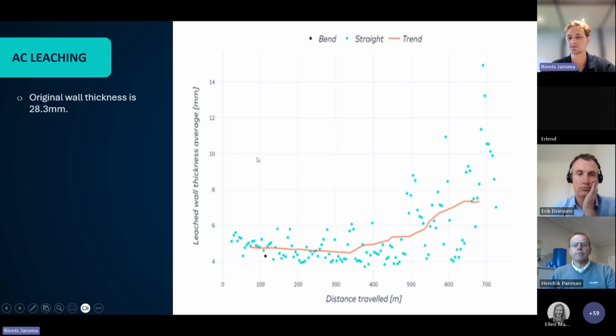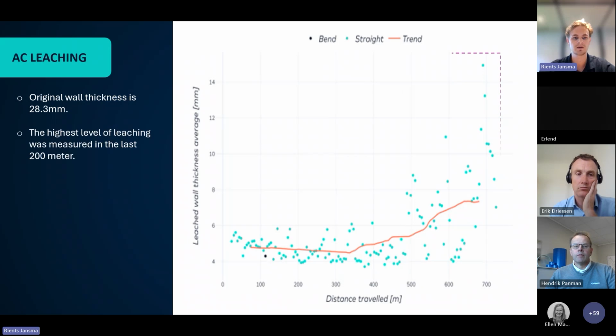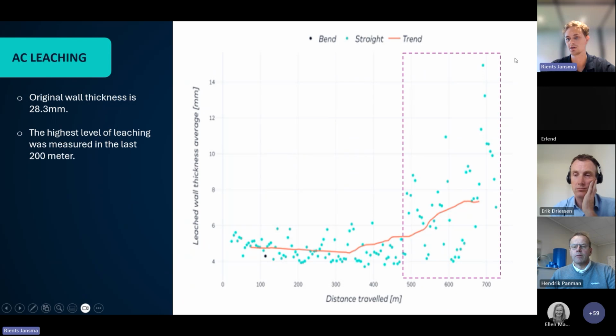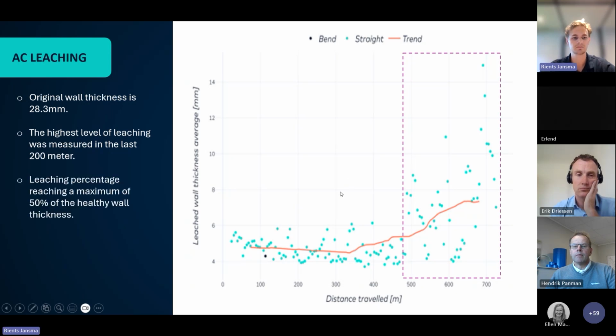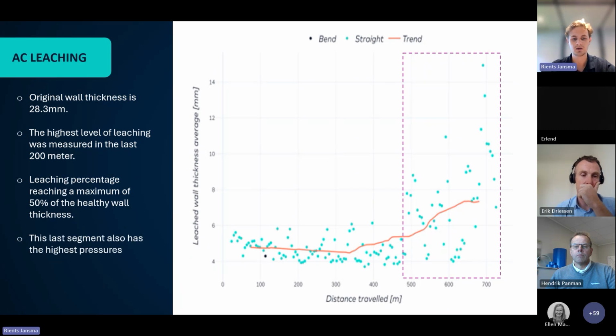So the original wall thickness is 28.3 millimeters, and the highest level of leaching was measured in the last 200 meters of the asbestos cement section. The leaching percentage reached the maximum of 50%. At the top, you can see it's more than 14 millimeters leached, which is 50% of the original wall thickness. What's interesting is that the last 200 meters, the last segment, also has the highest pressures within the tracé.